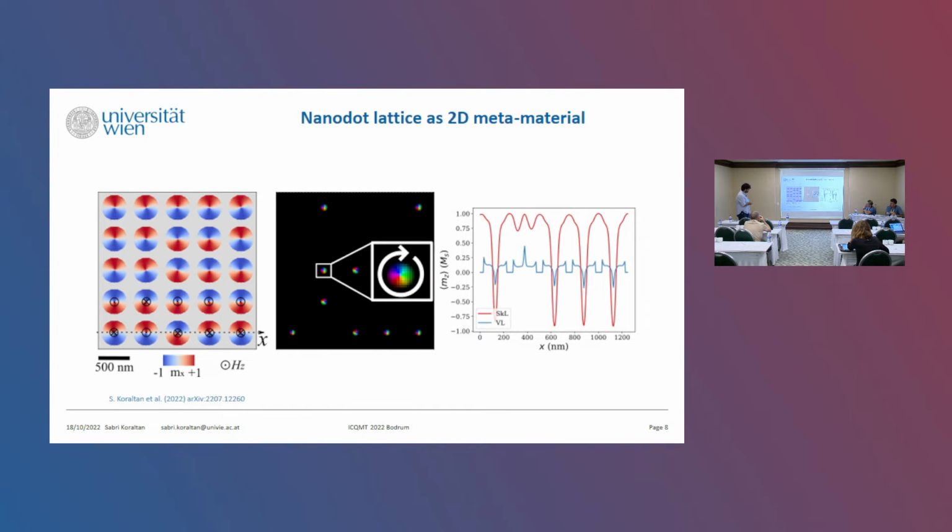And then in the next one, where it's anti-parallel, we see the skyrmion as plotted here by the magnetic induction map. And if you would then sample the magnetization along this line, we can see very nicely that whenever the vortex layer, where the magnetic vortex core points down, we obtain a skyrmion. And whenever it points up, then we do not have a skyrmion.